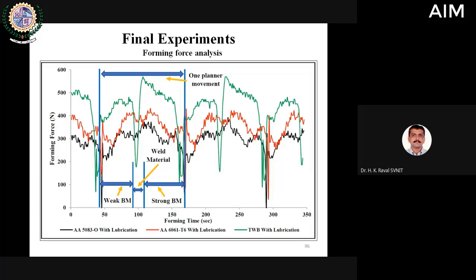But if you see, the green color is the trend of the forming of TWB. In forming of TWB, forming takes place of a weaker material, then weld material, and then strong material. And it depends where your starting point is. If the starting point is on the weld point, then the force would be different. If the starting point is the center of either the weak or strong material, the forming force pattern would be different. Here you can see that when material is forming, weak forming or strong forming, it has variations, and there is a sudden drop in the force at the junction or at the joint, and then again it rises, and again it drops, and again it rises.